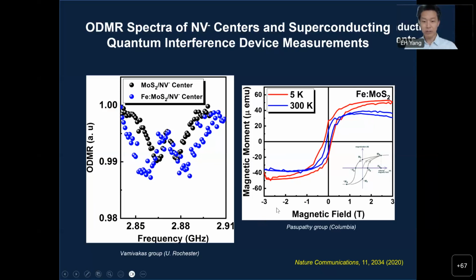Another independent measurement is SQUID, the superconducting quantum interference device measurement here, and you see a clear hysteresis curve here that only comes from ferromagnetic materials, all the way up to room temperature. At 300K, you still see coercivity, so it hasn't reached the Curie temperature. So this SQUID result shows this global or average effect, okay? You have this average value of the magnetic flux, and basically you show this coercivity, and this means that the Curie temperature is higher than room temperature.